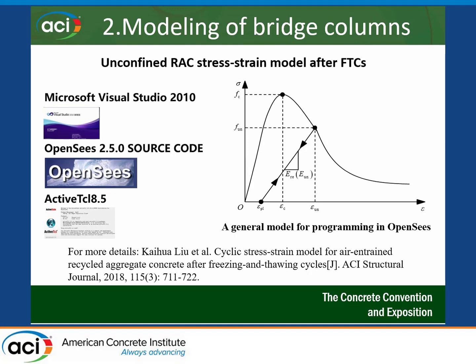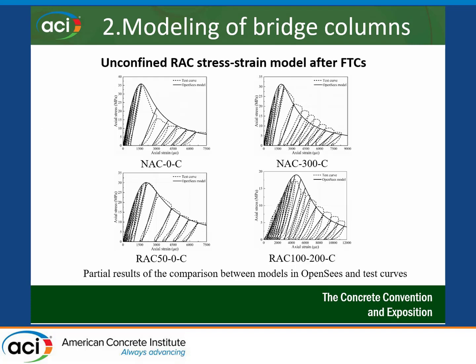In OpenSees, the general model for stress-strain behavior of concrete was modified to simulate concrete behavior under freeze-thaw cycles. Several specimens were tested under freeze-thaw environments in laboratory conditions and subjected to cyclic loading. The OpenSees model was validated against experimental results — the solid line shows the OpenSees modeling curve and the dotted lines are from the experiment — showing a very close match.